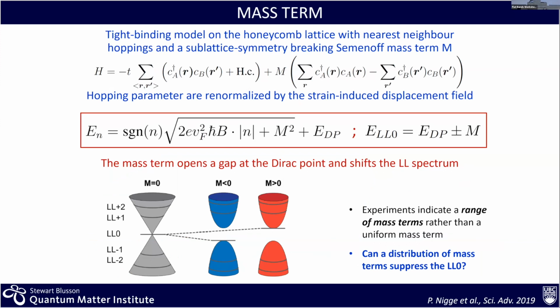So the model being used for the analysis of the data is shown here: a tight binding model with nearest neighbor hopping. What strain does is really renormalizing the hopping parameters in the system. So that's how we capture the strain. But now things are interesting if we go and add a mass term. The mass term is basically the symmetry breaking Semenoff mass term coming from the interaction between the graphene and the substrate itself.